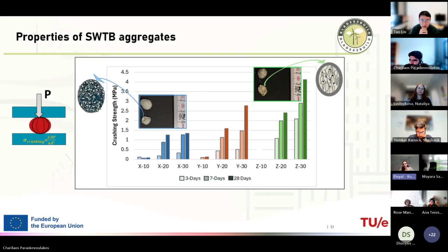When we discuss properties, of course, strength comes to mind. For these artificial aggregates, the crushing strength is one important parameter. This is achieved by crushing one individual aggregate. In these graphs, 15 different aggregates are tested, and those are the average values by recipe. What we see is that according to the used particle size of raw material, different types of aggregates were achieved. One of them is regular pelletization, and the other one is encapsulation. Both have different benefits, but it is obvious that with the encapsulation form, the strength of the aggregate and also the water absorption are increasing.